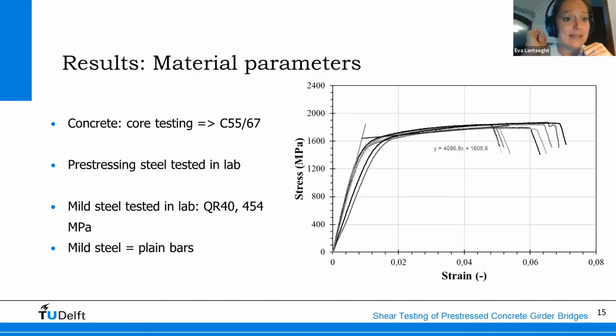We tested the pre-stressing steel. So here you can see the results of testing the pre-stressing steel coupons that we tested to find the stress-strain diagram. And we also tested the mild steel. The mild steel were plain bars, and we found that it had an average yield strength of 454 megapascal, so we could identify it as a QR, or it was shown on the drawings to be an old Dutch QR40, so a mild steel with design strength 400 megapascal. Of a characteristic yield strength of 400 megapascal, I should say. And we found an average yield strength of 454 megapascal, so a little higher than we expected. We expected 440.